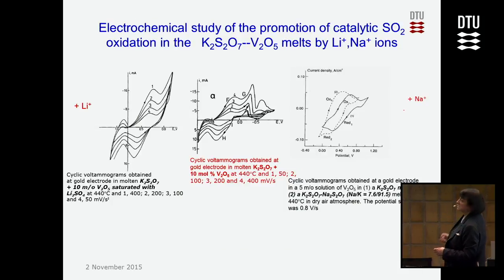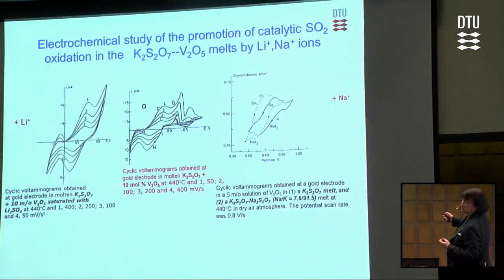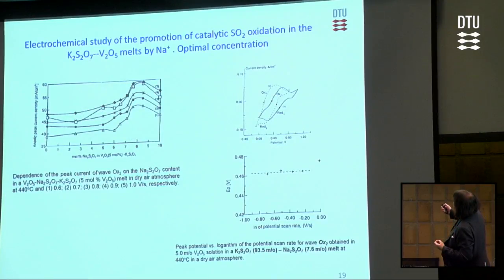Okay, now we studied the effect of cations. The well-known promoters in these reactions are sodium and cesium. I introduced lithium. Compare this reaction with this, and you will see the difference. The reaction, which was irreversible, becomes reversible with a small addition of lithium. Look at this: irreversible, reversible, sodium, small percentage. Look at this. We can actually find the optimum sodium concentration in the catalyst. If you look at sodium content in the Topsoe catalyst, you will see we were very close.